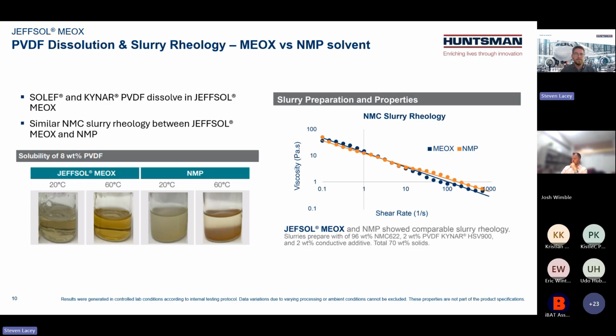And here we can see when you take 2 extremely well-known brands of PVDF, they both readily dissolve in MEOX as well as NMP. And when we increase the temperature to higher temperatures, obviously you have better solubility. On the right, we can see once you use this system and make an NMC slurry cathode, here's the rheology data, where it's very similar across all shear rates, showing that the viscosity does not really change between NMP and this new alternative, which is MEOX.